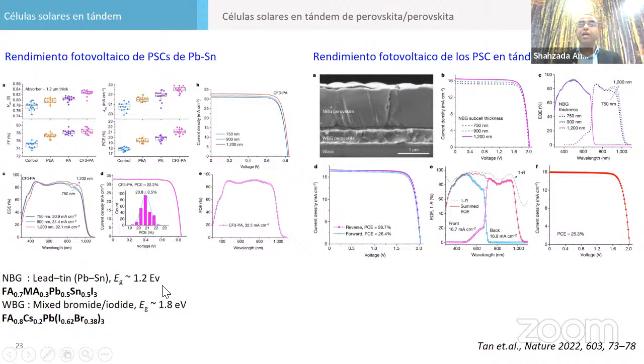So you can have a perovskite tandem. Another perovskite with a high band gap, like methyl ammonium bromide based, they found a new composition which has a band gap of 1.8 electron volt. They put the narrow band gap perovskite, lead and tin, at the bottom and the wide band gap perovskite of 1.8 electron volt at the top. They have recently achieved 26.7% efficiency with this perovskite tandem. So this is also a very good approach to increase the performance of solar cells.